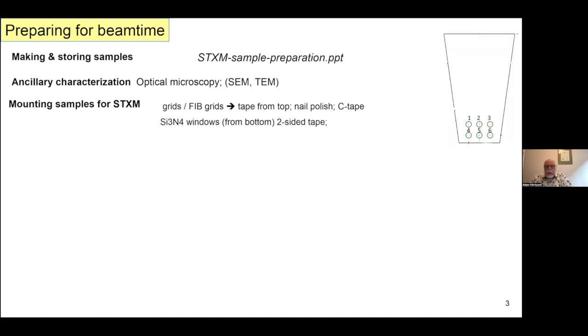So as Karina said, there are various ways of putting your sample into the STXM, either on a TEM grid or full 3mm grid, or these half grids for focused ion beam preparation of samples. You can attach them to this 6 or 8 hole plate in various ways. I personally, with grids, like to tape them from the top with single-sided tape because it's very easy to remove that and retain your sample. Some people like using very sticky carbon tape, double-sided sticky, and it's impossible to get that material off without completely mangling your grids. Nail polish, I know the MAX IV team likes to use that and uses it very successfully. So there are a bunch of ways. Trial and error never hurts.